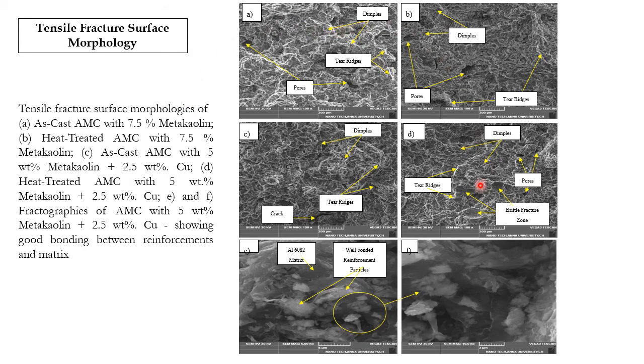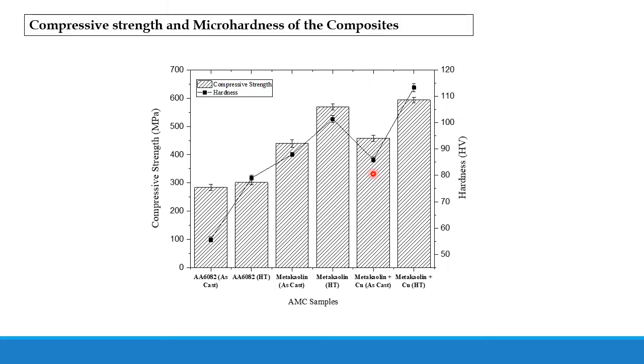So the tensile fracture modes shows a mixed mode of fracture that includes tear ridges, dimples, and brittle fracture zones. So a good bonding between the powder and the matrix is also observed from some images. A considerable improvement is observed on the compressive strength as well as the hardness also.